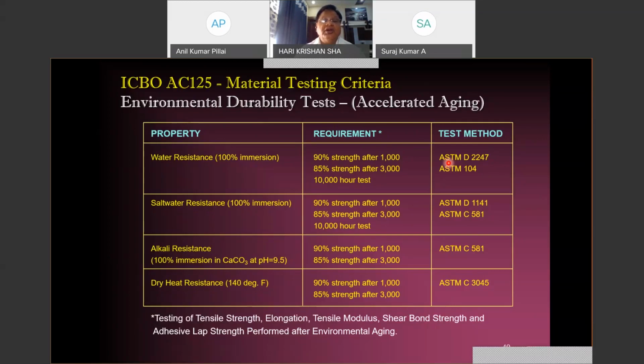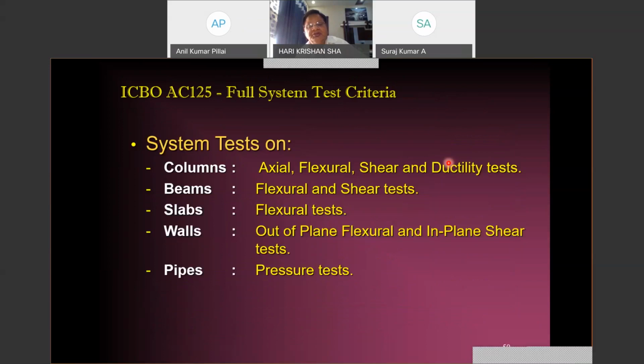As far as the ICBO requirements are concerned, the system tests are to be conducted when this material is used for columns, beams, slabs, or for infill walls. And these tests are to be conducted in compression, tension, flexure, and some tests are also required for ductility. When this material is used for beams, then flexural and shear tests are obviously required. In case of slabs, which are basically flexural members, a flexural test will be sufficient. In case of walls, the out-of-plane flexural and in-plane shear tests are required. And when the material is used for pipes, obviously the pressure test is required to be conducted.